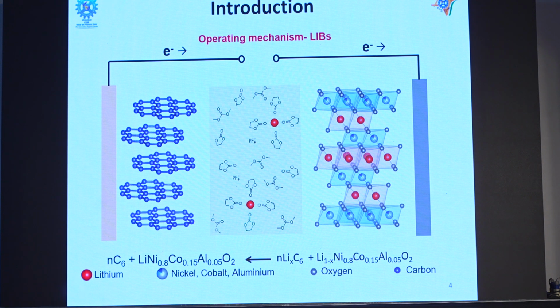So now you heard a word, intercalation. Intercalation is nothing but lithium ions, or any ions, migrating from one electrode and getting into another electrode without disrupting its original crystal structure. So why am I talking about lithium-ion batteries here? Because sodium-ion batteries or magnesium-ion batteries have the same electrochemical mechanism as a lithium-ion battery. They also use intercalation electrodes mainly. And there are other types of electrodes, but I'm not going into the details of these electrodes.